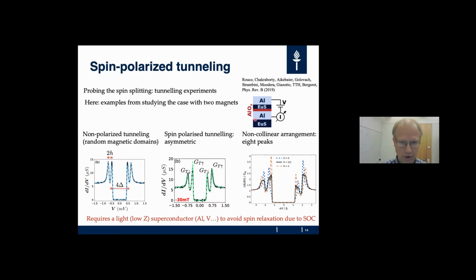In this case, we have two superconductors. But I think in this experiment, actually, the exchange field was present only in one of them. If you magnetize this sample—so in this first case, they were not magnetized, the magnetic domains were random, so the peaks were kind of equal height.